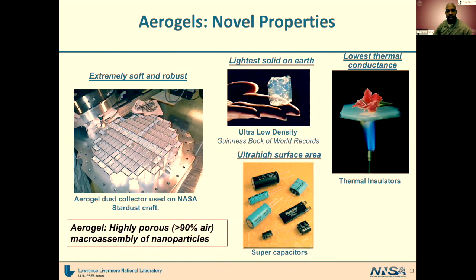So here is just a highlight of some of the novel properties of aerogel materials. There was a program by NASA focused on trying to collect dust from a comet. This application required a material that was both soft, so that the particles you're capturing would not be damaged, but also robust, because you would have to hold these particles and transport them from space back to the Earth. And so the material they chose was a low density silica aerogel.